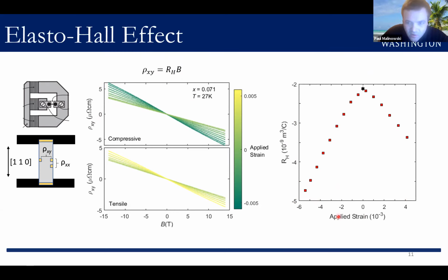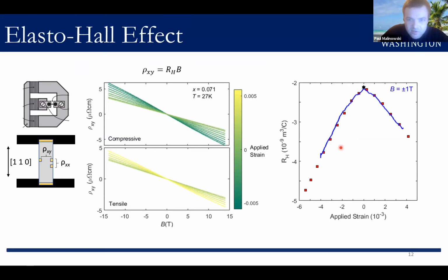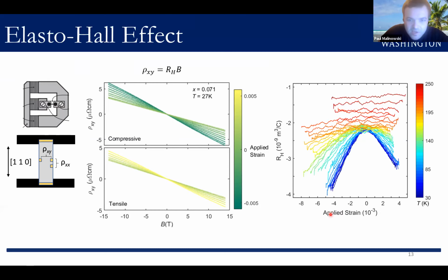Now we can also measure this quantity a different way by fixing field and sweeping strain instead, which results in this blue trace. And these two methods agree, and this latter method is much quicker, which allows us to then track the temperature dependence of the behavior, which I'm now showing here. So this is the same type of fixed field variable strain trace of the Hall coefficient as a function of strain, with each color corresponding to a different temperature. And what you see is that this phenomenon is strongly temperature dependent, with the large nonlinearity developing at low temperatures.